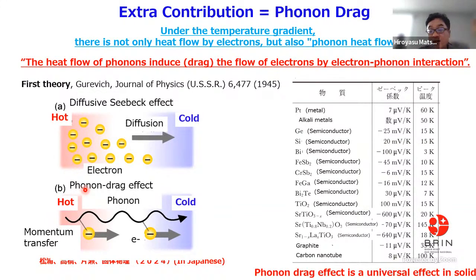So when we apply the temperature gradient, this figure shows this is the hot side, this is the cold side. In this case, the electrons move from the hot side to the cold side, and then finally we can get the voltage. This is the usual imagination. But when we apply the temperature gradient, we have an additional heat flow. This means we have additional heat flow coming from the phonons. So phonons are also an origin of heat flow.